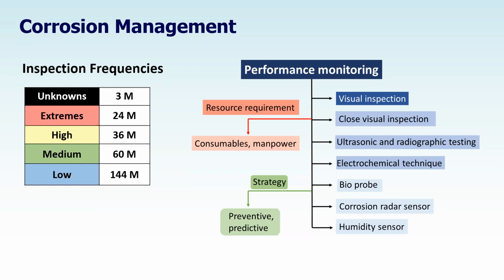Risk-based inspection frequencies are based on the inspection results, such as corrosion allowance or the wall thickness. Performance monitoring and visual inspection can be performed very often. It doesn't require any special arrangements. Close visual inspection, ultrasonic and radiographic testing, and electrochemical techniques need to be done by a trained person with the appropriate time frequency. Advanced sensing technologies, bioprobe, corrosion radar sensor, and humidity sensor will help to monitor the remote area and confined area equipment continuously, and can avoid the scaffolding and other arrangements needed to inspect remote area equipment.